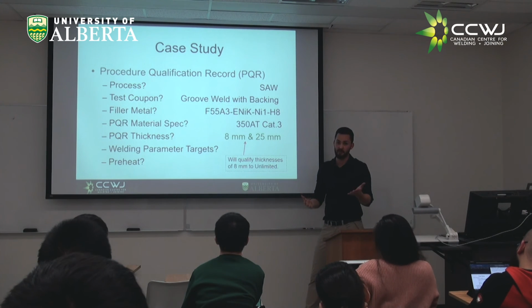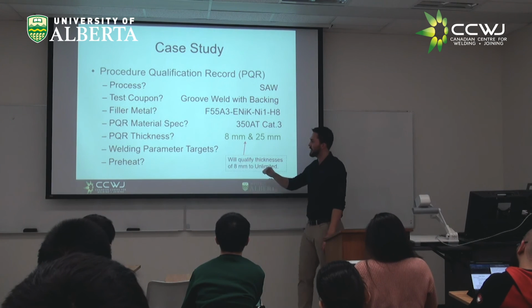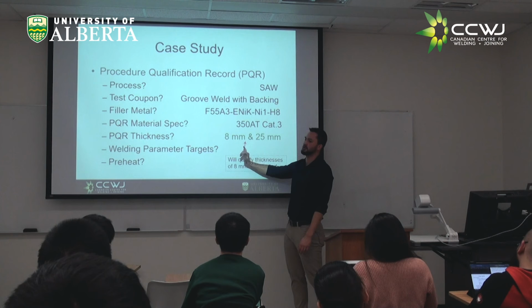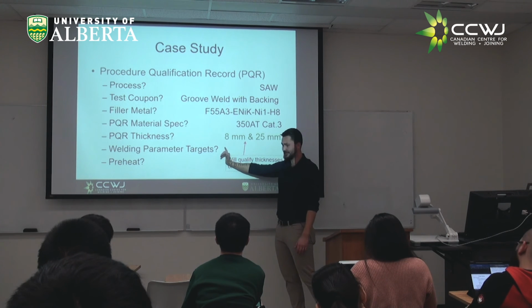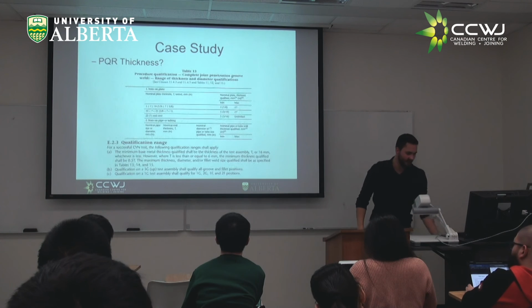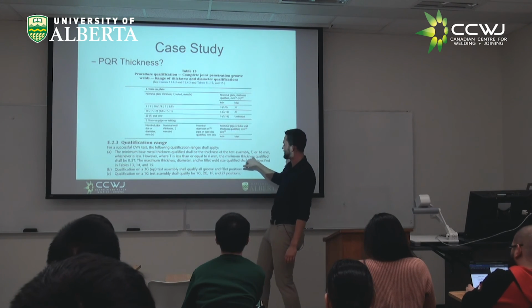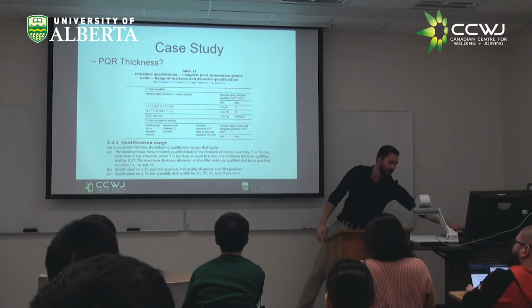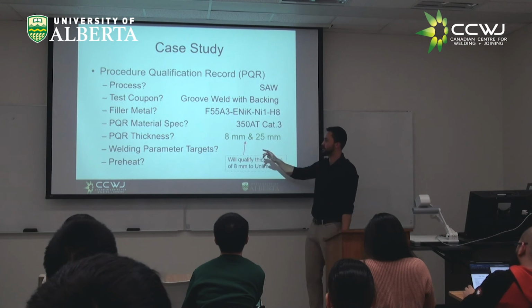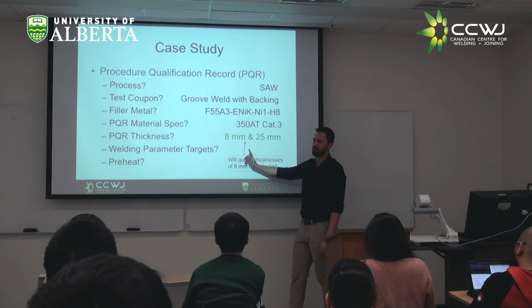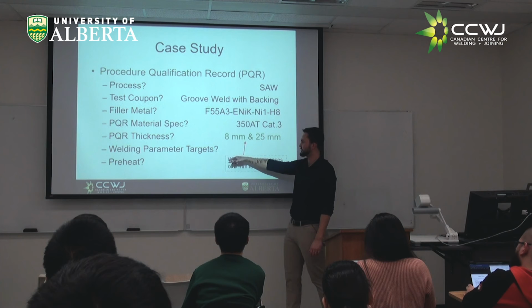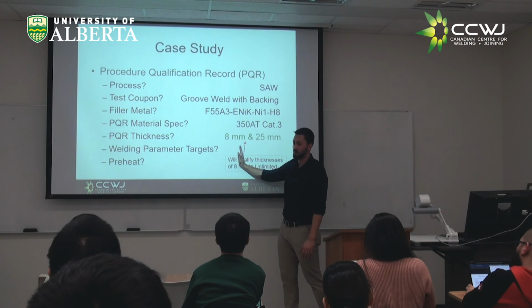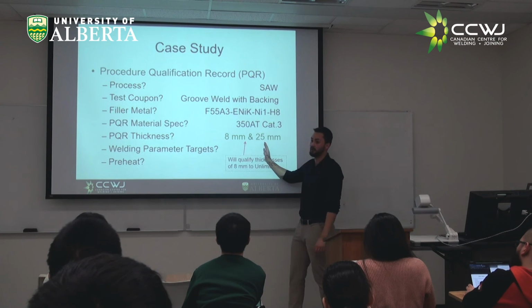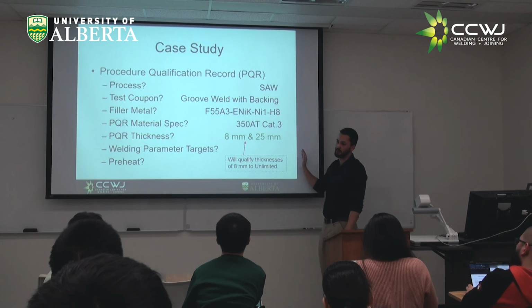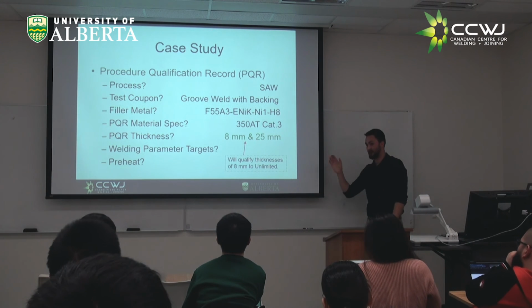If you want to qualify a weld from 3 millimeters all the way up to unlimited, what you essentially have to do is test at 6 millimeters, because if you go back up the slide, they actually say if you test at less than or equal to 6, the minimum thickness is half of the thickness. So if you want to be good from 3 to unlimited, you have to test at 6 millimeters, then you have to test at 10 because you get 12, or you can test at 12, one of the two. So the 6 millimeters will get you 3 to 12, then you test at, let's say, 10, which gets you 10 to 20, then you test at 25, which gets you 16 to unlimited. A lot of testing, a lot of money.